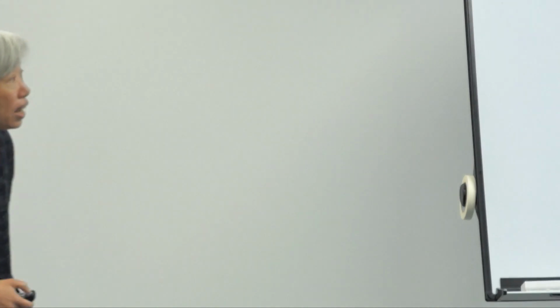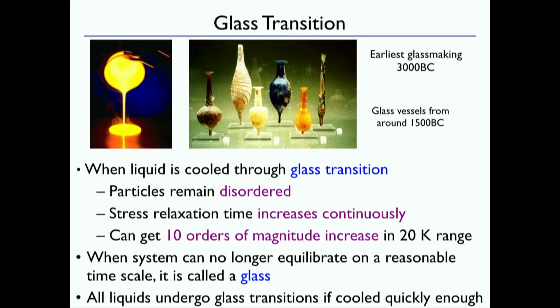All right, and the thing is that it increases continuously, but enormously. It just shoots up so that you can get orders of magnitude increase in just tens of degrees. Okay, that's very typical, this incredibly fast increase. And so then it just goes out of range, right? It increases so fast that it goes out of range. You cannot wait long enough for it to equilibrate anymore. And if you can't wait long enough for it to equilibrate, it has fallen out of equilibrium, and it is a glass. That's what you call a glass.